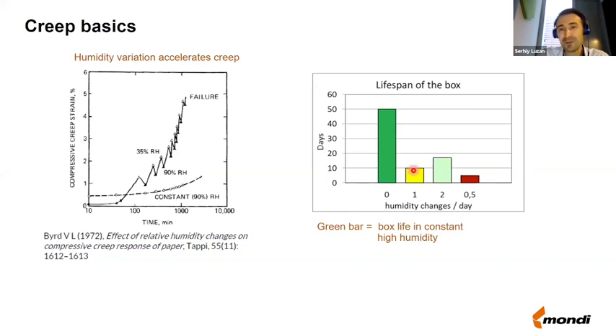And then if you further reduce, or let's say depending on how many cycles a day you have, this lifetime will be different. Interestingly, if you have 2 cycles of changing humidity per day, the lifetime of the box will actually be a little bit higher than for 1 cycle a day. But for half a cycle per day, the lifetime will be even lower. So you may ask, why, if we have 2 cycles per day, is the performance better than if you have 1 cycle a day?